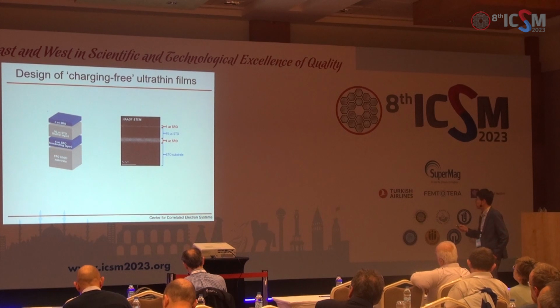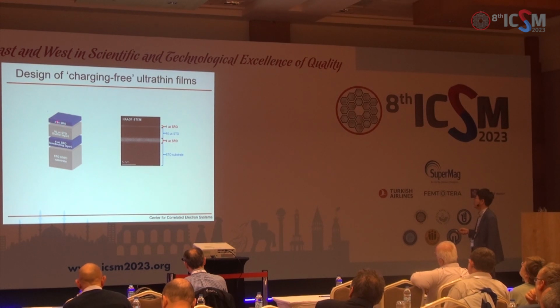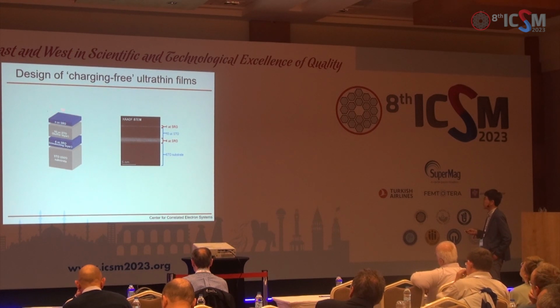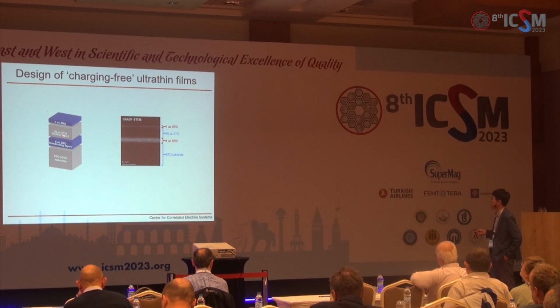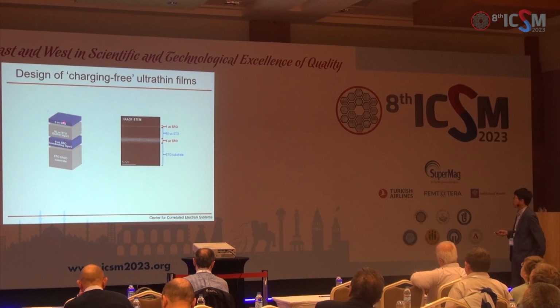So we devised a heterostructure system as shown here. We have an STO substrate as usual. We grow 4 unit cells of strontium ruthenate that provides electrons. And here's 10 unit cells of STO, and we grow N unit cells of SRO. Using ARPES, because it's surface sensitive, we only look at this top strontium ruthenate layer. However, this 10-unit-cell STO is thin enough that the current leaks through it to the top strontium ruthenate layer. So we don't suffer from this charging problem.